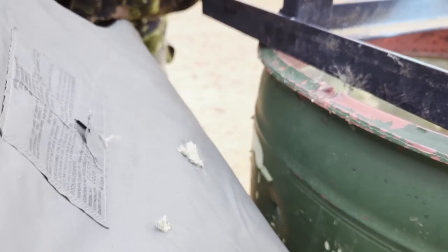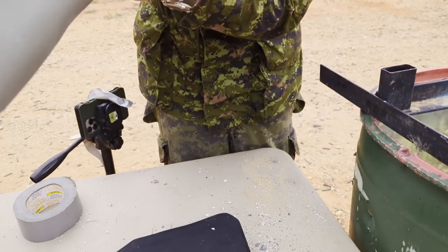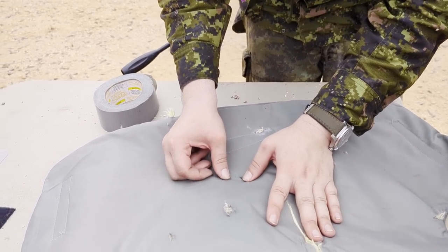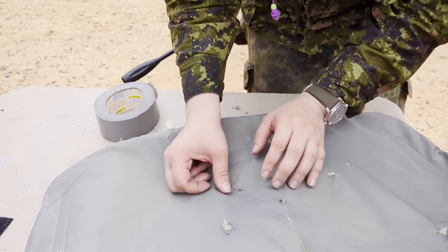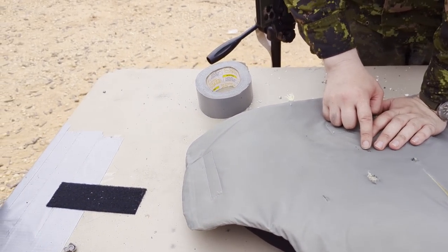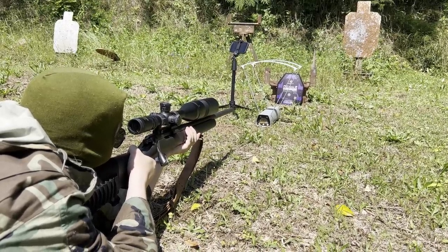The Colossus plate stopped the round — it stopped in the Kevlar. This round penetrated the plate but was stopped by the Kevlar backing, suggesting it has some measure of strength beyond the BX SAPI. The Colossus plate is supposed to be standalone though, so the Kevlar is more of an afterthought. I contacted Adept Armor and asked for a fresh plate to test.